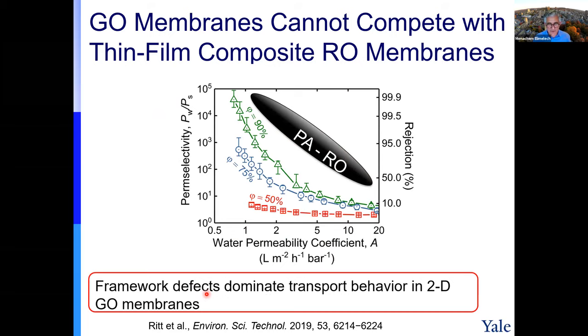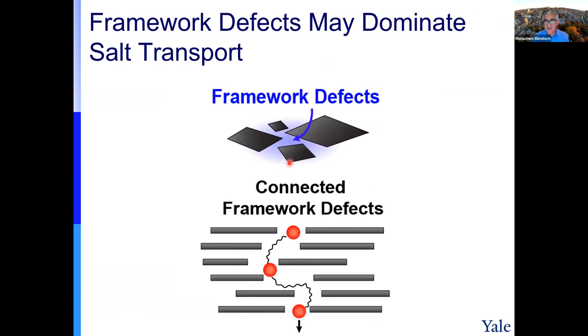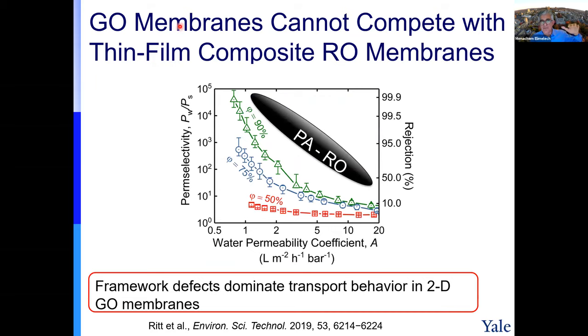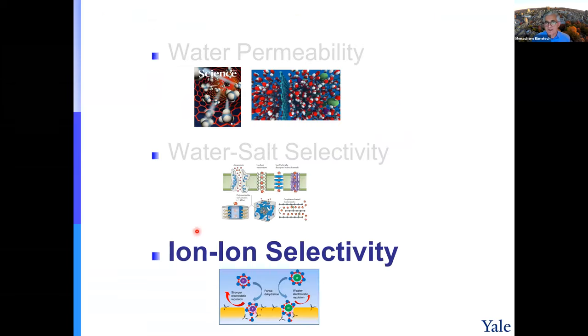And this is because of what we call framework defects. Again, you can think about it: you form one layer and then you form another layer above it, and you will have all these framework defects interconnected. Eventually, you need to build a very, very thick membrane to avoid these interconnected framework defects, but then you reach a permeability which is very, very low, and then it's not useful for desalination. Okay, so this was about this membrane.